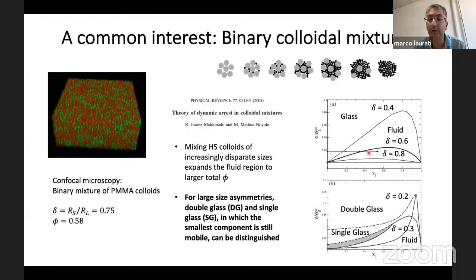So essentially it shifts the characteristic volume fraction of the glass transition to typically larger values at intermediate mixing. But actually even more interesting is what happens when you come to large size asymmetries, where effectively you can distinguish between different kinds of glasses. So you can distinguish, for example, between a double glass state, in which both components are dynamically arrested, and instead a single glass state in which one of the components, typically, of course, the smallest component, remains mobile while the large component is frozen.